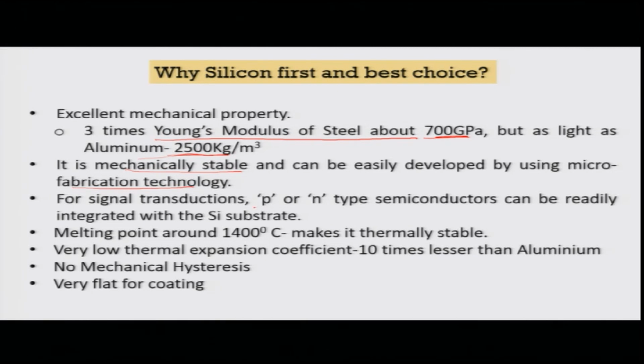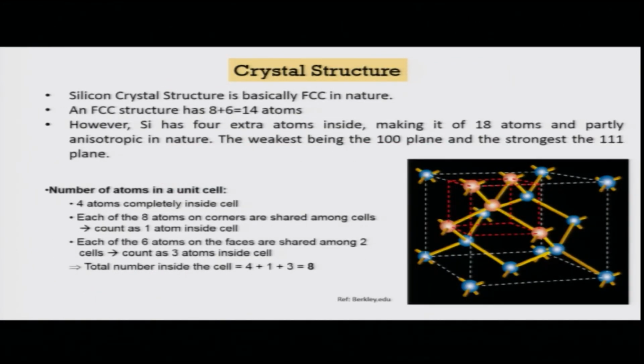For signal transduction, you can make p or n type semiconductors that can be readily integrated with a silicon substrate. So, you can develop various semiconductors also. In fact, the semiconductor industry helped the growth of silicon. Melting point is around 1400 degree centigrade, so it is thermally quite stable for most engineering applications. Not only that, it has a very low thermal expansion coefficient, 10 times lesser than aluminum. Now, at a smaller scale, the way it helps is that if there is a thermal expansion in the system and the other parts of the system would not be expanding, then thermal stress will be generated in the system. So, the chance of such generation is much less in silicon. It has no mechanical hysteresis and it is very flat for coating. So, all good reasons for silicon to be used as the most important MEMS material.